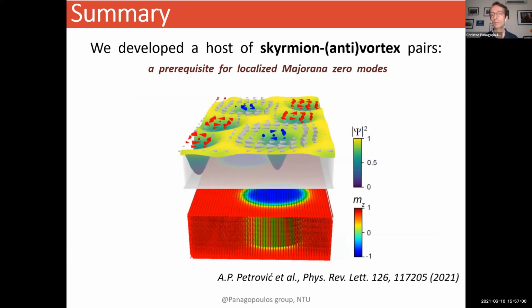But nothing stops you from having a higher temperature superconductor for as long as you can also stabilize skyrmions at high temperature. Now, our skyrmion platform can actually have skyrmions all the way up to room temperature. This is the work that we showed for the first time when Anjan was my postdoc here back in 2016, 2017 with Raju. So that is not a problem. The superconductor, yes, indeed, you should be able to get a high temperature superconductor, or not necessarily an oxide, could be other superconductors, and do that for as long as you can have the right size of coherence length. But this is the first proof of concept.